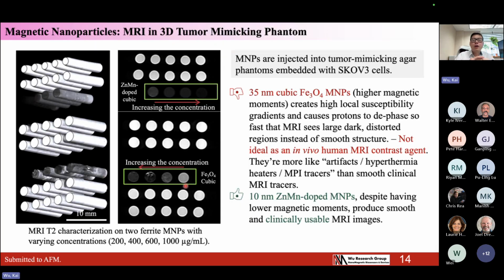So lastly, we already showed you that some particles are biocompatible and some particles are good for hyperthermia therapy for the tumor treatment. Now I want to further demonstrate that this particle can also be used for tumor imaging in the MRI system. The full name is magnetic resonance imaging. So we prepared some phantoms of these nanoparticles embedded in agar phantoms with SKOV3 cells. The top panel shows zinc manganese doped cubic particle with 10 nanometer size. The bottom panel shows the MRI imaging of the iron oxide cubic particle with 35 nanometer. You can clearly see that for the bottom panel, the MRI imaging is not very smooth. You can see some bright color, some dark color, right? This not very smooth MRI imaging, we call it an artifact.